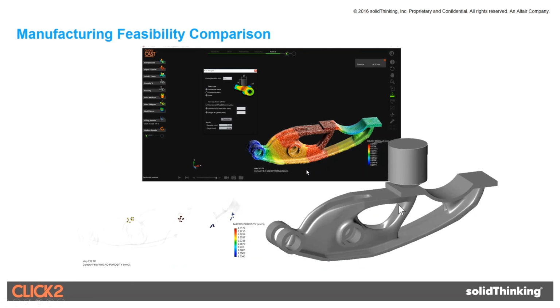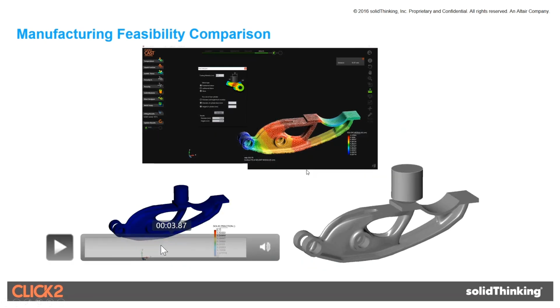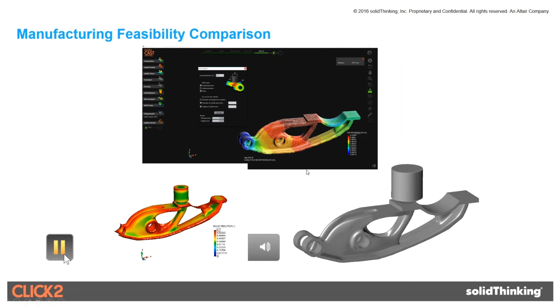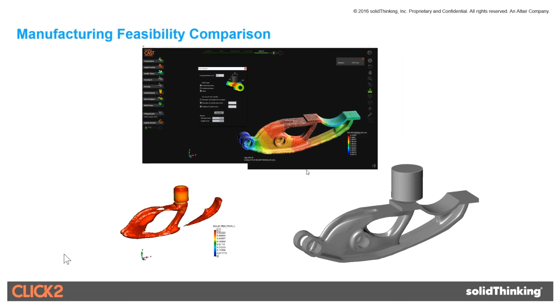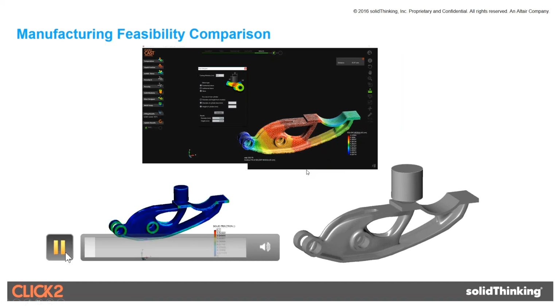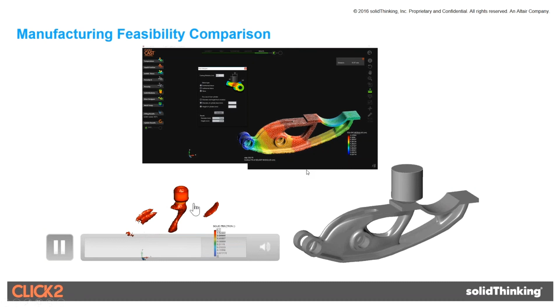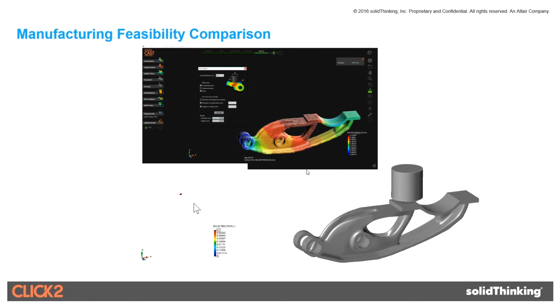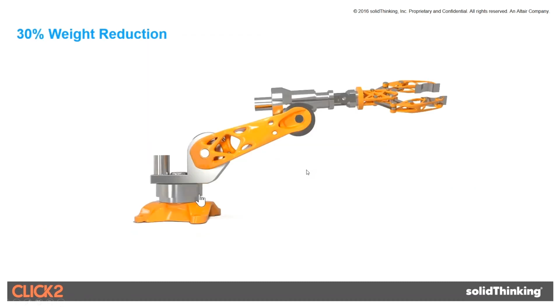So, if you look at this particular case, it's showing you a big blob of porosity right in the center where the junction is. Whereas on the right-hand side, if I measure the area of porosity, there's an 88% reduction, from 34 cubic millimeters to 4.3 cubic millimeters in one location. So what it's trying to tell you is that not only have you lightweighted the structure, but interestingly, it also becomes easier to cast because the porosity is 88% less.